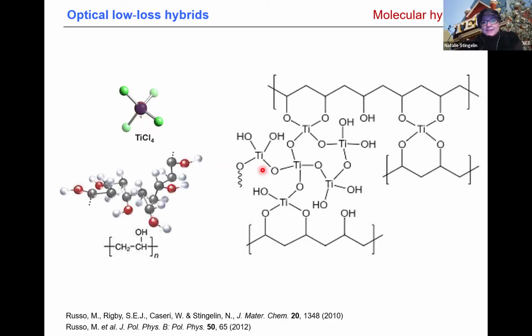It's a polycondensation. So you split off HCl in the case of titanium tetrachloride, or alcohols if you have titanium isopropoxide, and you start to form this inorganic polymer, titanium oxygen titania. Actually the reaction to titanium dioxide is prevented because the precursor reacts with the hydroxyl group of the polymer.